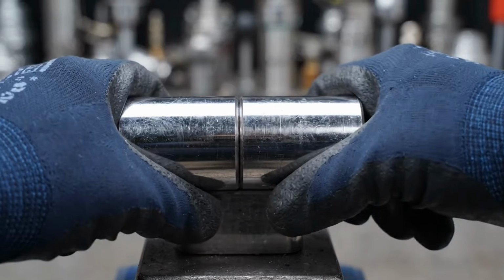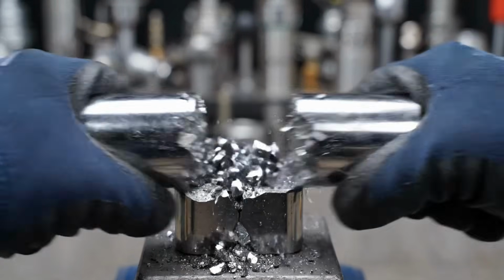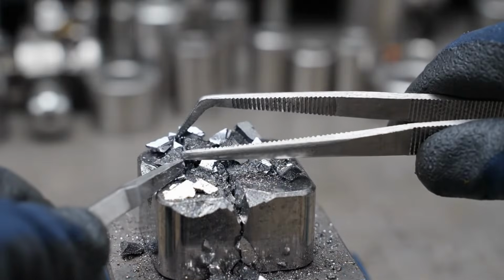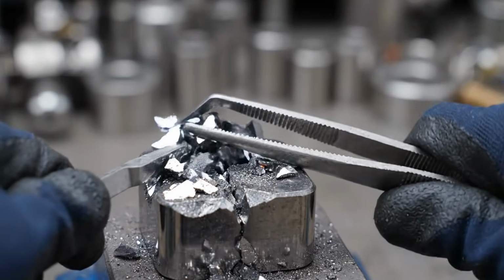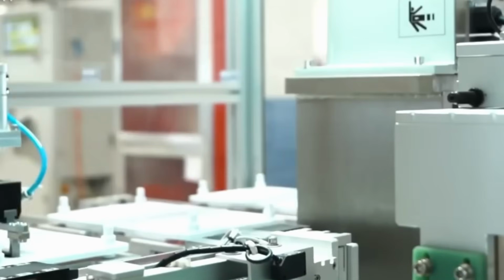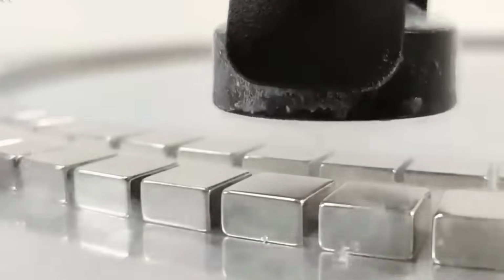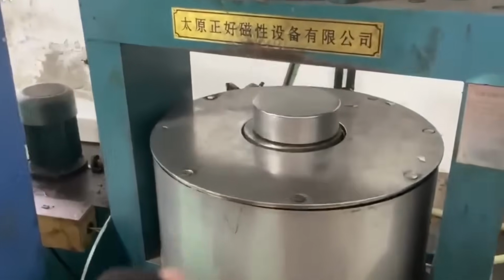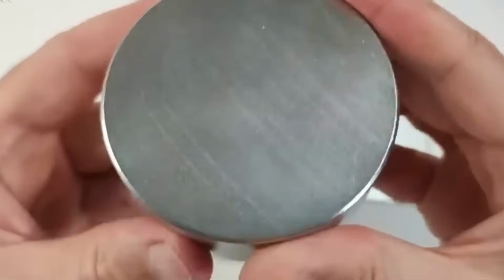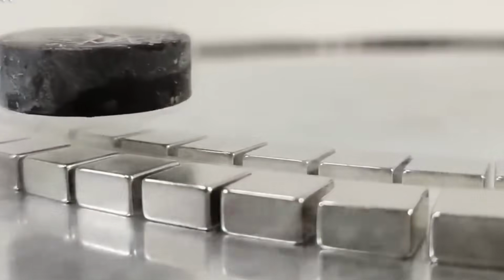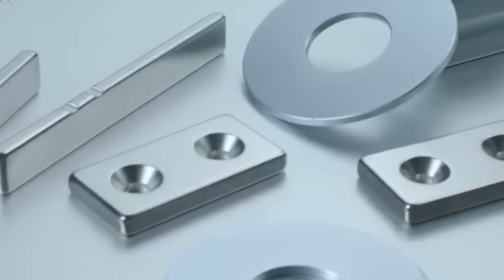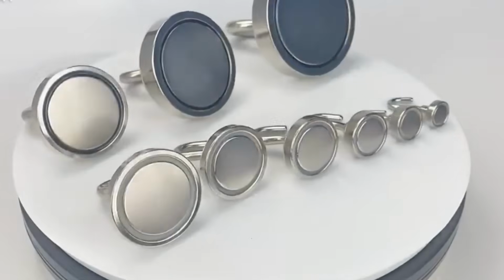After concentration, the material is dried and undergoes further purification processes. In ferrite magnets, iron oxide is mixed with barium carbonate or strontium carbonate in defined proportions. In neodymium magnets, the preparation is more delicate because a precise combination of neodymium, iron, and boron is required, sometimes with small additions of dysprosium, praseodymium, or other elements that improve temperature resistance or coercivity. Coercivity is the magnet's ability to resist demagnetization.